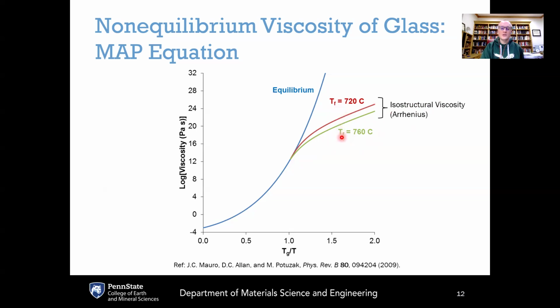If you were to cool the supercooled liquid very rapidly, you would fall out of equilibrium at a higher temperature. And this green curve here shows doing exactly that. So fast cooling here gives a higher fictive temperature. If you were to cool more slowly, the system has more time to stay in its metastable equilibrium, and it only falls out of equilibrium at lower temperatures, in this case at around about 720 degrees C. And what you can see is that the value of this fictive temperature has a pretty big impact on the viscosity of the glass.